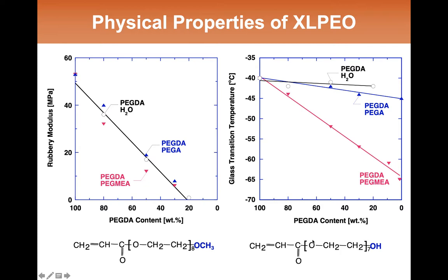Now, if you come back to the original picture by Bayer, with the sulfur cross-linking in natural rubber, there was an enormous change in glass transition temperature as the cross-linking density changed. And so we can look at that for this case as well. So the sample that's most highly cross-linked is the one that's made entirely, 100%, from the diacrylate, 100% cross-linker. And that material has a Tg of about minus 40 degrees C. You dilute that cross-linker down with water and reduce the cross-link density, and it barely moves the glass transition temperature. So unlike the case of natural rubber, this is a situation where even though the cross-link density is going down, the glass transition temperature is barely moving.